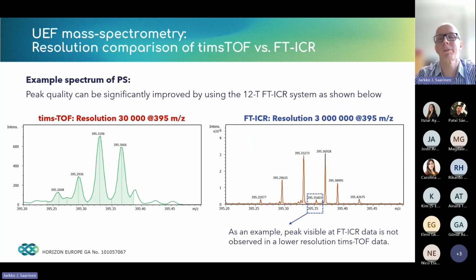One example here shows the difference between the timsTOF and the high magnetic field FTICR system. As mentioned, the resolution on the FTICR is significantly higher, in this case 100 times higher. Here's an example of the 395 mass over charge peak, and one can clearly see the difference between the resolution of the timsTOF and FTICR. FTICR has much narrower peaks, and one can also identify different peaks that one cannot see in the timsTOF spectrum because it's a convolution with a lower resolution. But it's still worth emphasizing that this timsTOF device is very well suited for plastics analysis.